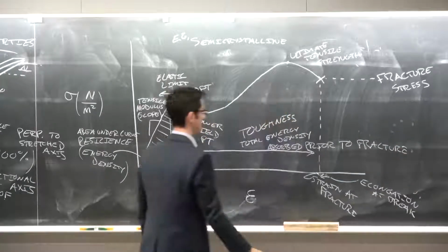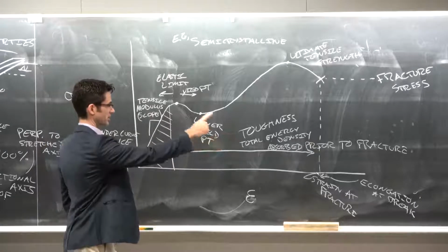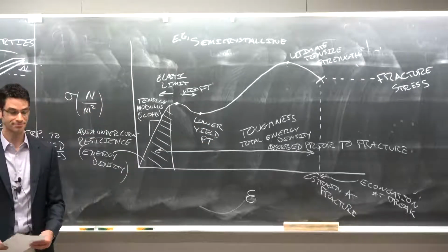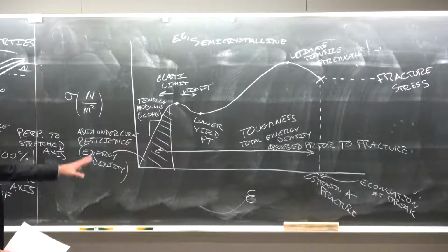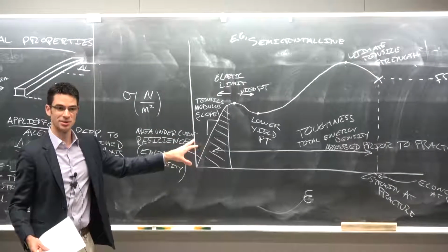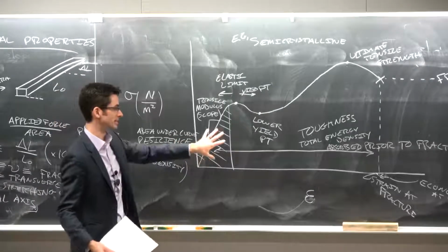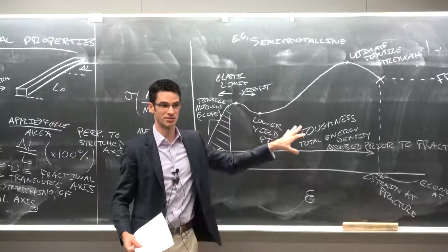And that is, again, the integration of the entire stress strain curve is the toughness. Now, interestingly, that includes the resilience. So the resilience is always smaller than the toughness. The resilience goes into this calculation of the toughness.